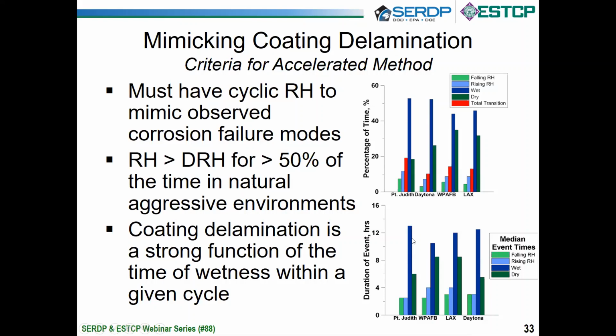So if you have a complex coating system, like I mentioned before, and showed in the data that Erica Maka had done, you need a certain amount of time before you can activate inhibitors, or in the case of metal-rich primers, a certain amount of moisture has to ingress before you can get these galvanic effects that you're looking for. So again, this is an important thing to consider as we're doing tests. So these actually came from sensor data that has been out in the world. And for those of you that don't know, there are other programs funded by both the Navy and the Air Force that have multiple sensors at multiple locations, gathering large amounts of data on this.